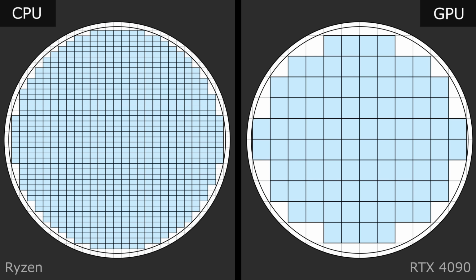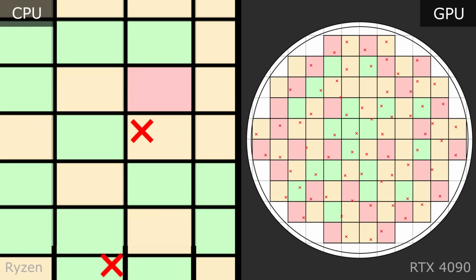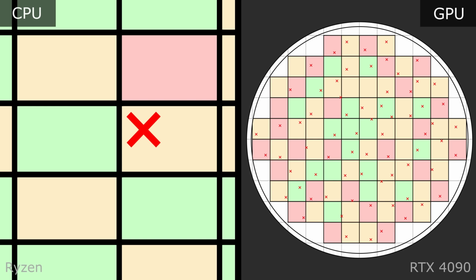The fabrication process is extremely delicate, and even minor microscopic variations can reduce the quality of the resulting chip. Despite everyone's best efforts, the quality of the resulting silicon varies somewhat randomly across the wafer, and a small number of unfixable defects per wafer are also inevitable. When the wafer is later cut into individual chips, even though they were meant to be identical, each chip will have differing characteristics. To avoid wasting silicon, IHVs may therefore take the resulting chips and do what's called binning.